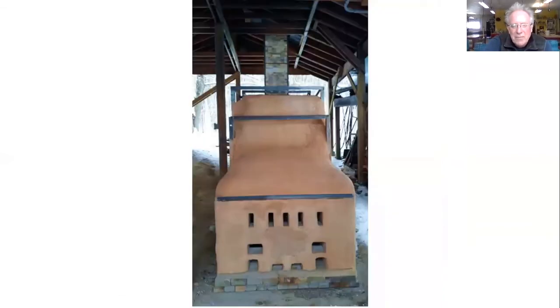And this is the bottom end of the kiln at the firebox. And those slots on top, the five slots, are for the steel grate. So the bars fit through those openings there. The second larger holes in the middle are just extra air that can come under the grate bars if you need it. And then the very bottom ones are what we call mouse holes. Those are additional air. And also we feed the mouse holes with wood during the firing. So the air is preheated before it enters the chamber.